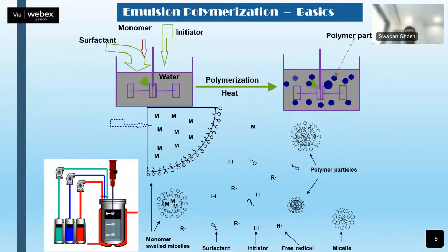For example, if you want to create a different range of particles after some time, during the process, if after 3 hours I add a little bit of surfactant, it will create new micelles. So particles will actually start building there again. In other ways, the control is much more because these are semi-continuous systems. It is a starved condition in the sense I have water, I am adding surfactant, I am adding monomer. If I don't add initiator, the reaction will not take place. If I add surfactant, water, initiator, but don't add monomer, the reaction will also not take place.